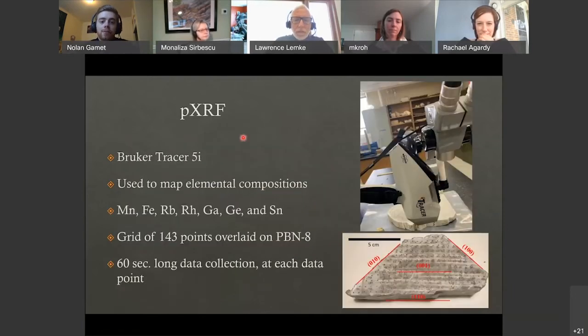For the pXRF, we use the Bruker Tracer 5i, which is this gun-looking machine over here that was attached to this in-house apparatus. This device shoots X-rays into the sample and it produces these spectra on this program called ARTAX. And then these spectra were used to map the elemental compositions. The elements we chose are listed here, and we chose these elements because they were above the detection limits of the device. Prior to doing the PXRF tests, I overlaid a grid of 143 points, each spaced at equal increments of 5 millimeters to maximize the resolution of the final 2D images. Each increment was approximately 60 seconds long.